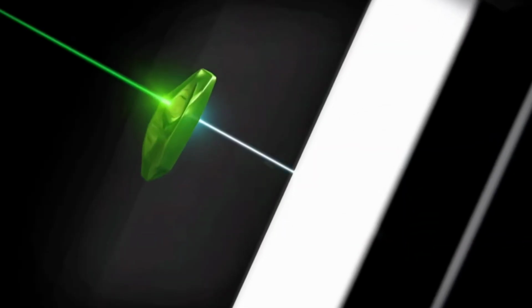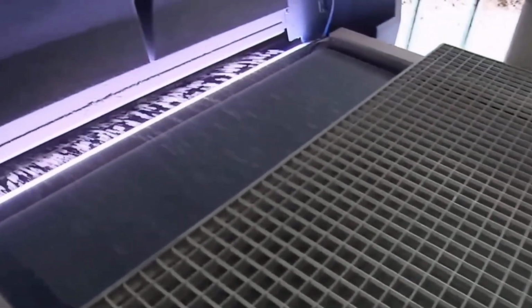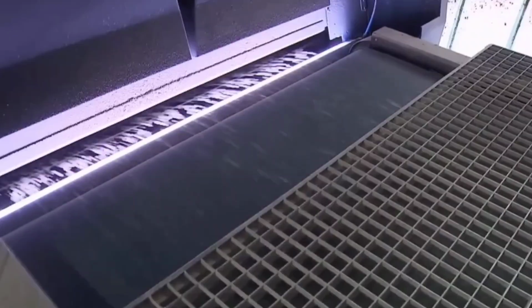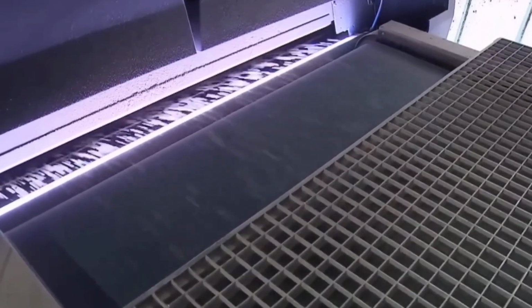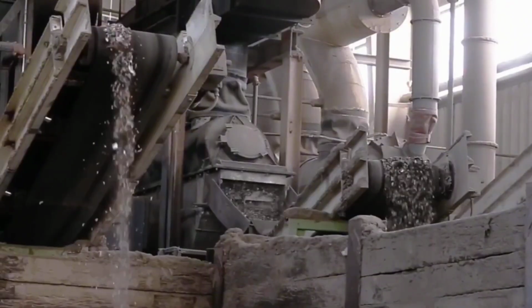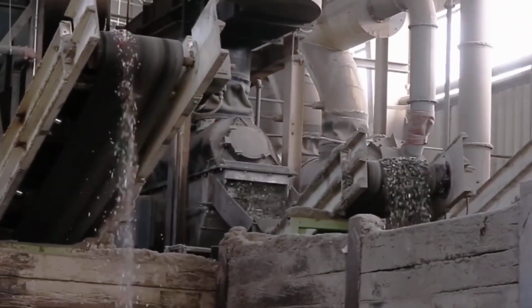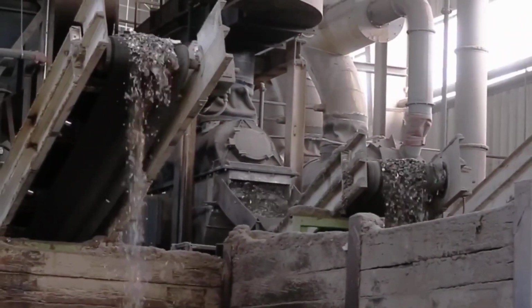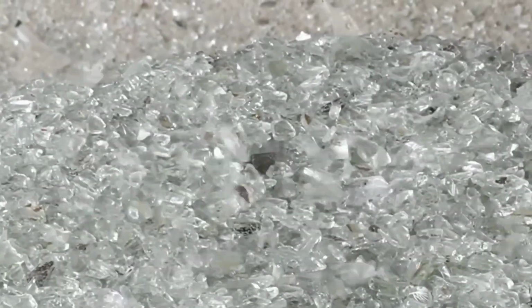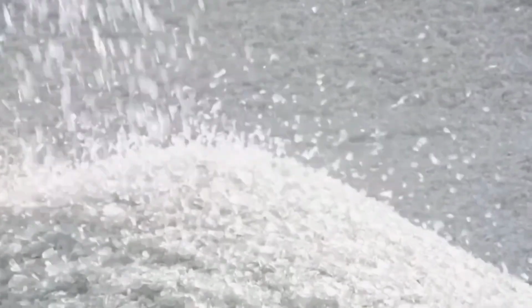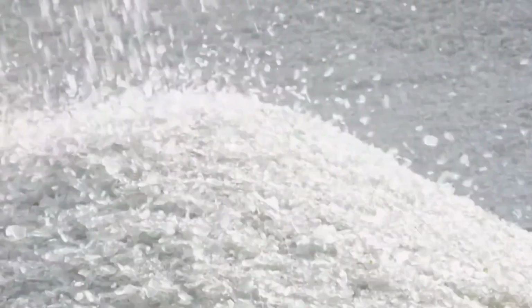After screening, the material passes through optical and magnetic sensors, where industrial cameras and metal detectors analyze each moving stream of cullet. These sensors can detect even microscopic contaminants, such as ceramics, stoneware, or metal fragments just a few thousandths of an inch wide, and remove them instantly with pinpoint air jets. In modern foam glass facilities, this system achieves up to 99.9% accuracy, virtually eliminating any impurities that could affect the closed cell structure of the final product.